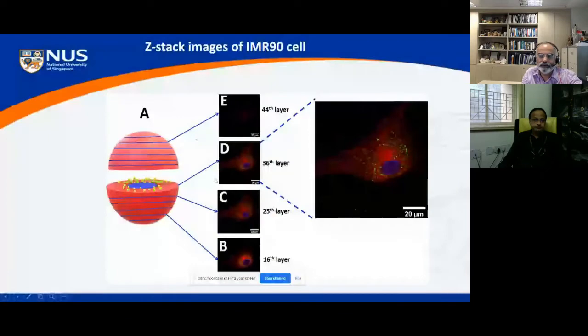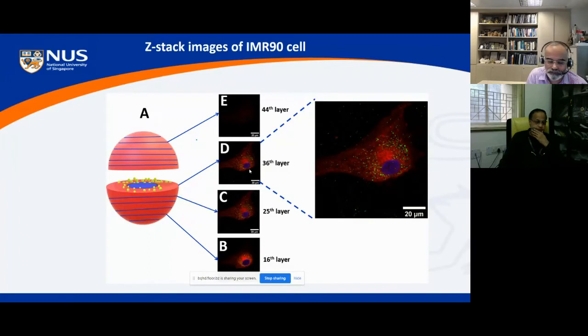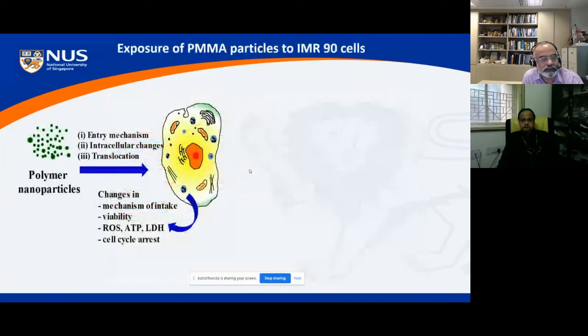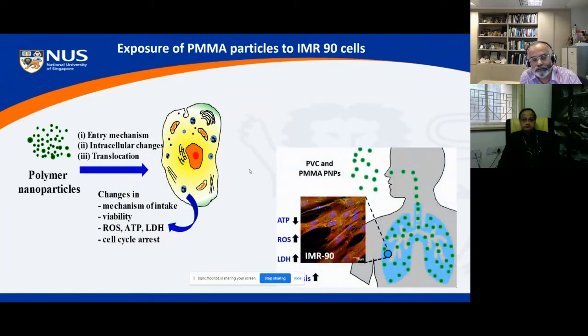So, obviously people will ask, when you put the cells and then add your particles, do they actually enter? How do you actually know whether the particles are inside? So under the confocal microscope, we can do a cross-sectional analysis of the images, right? So we take the image and then do different sections. Yeah, so under different layers, you can still see the particles. And that tells us that if there were no particles inside the cell, we would not see such optical images. Yeah, so that gives us an idea that what we are showing is actually the particle inside the cell. So these are some of the things we want to do with this, and we have been doing it, and we published quite a few.